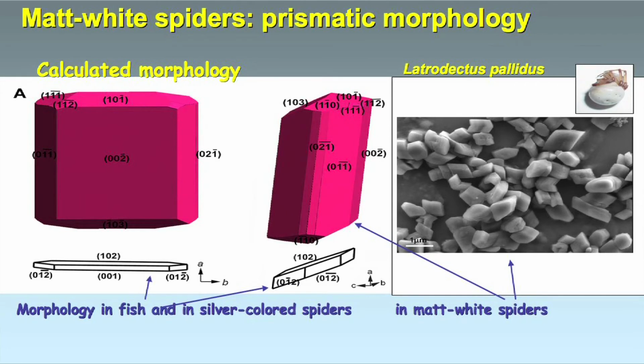Now we have indeed what we were talking about and what we were expecting. So the matte white spiders, different from the silver spiders and from the fish, develop crystals in a morphology that is what we would have expected to obtain without any interference from the organism. In the matte white, the answer is quite simple. There are no crystal plates, no periodicity, no photonic arrangement. Light is just dispersed, scattered, and reflected at random. And this gives rise to the white color.